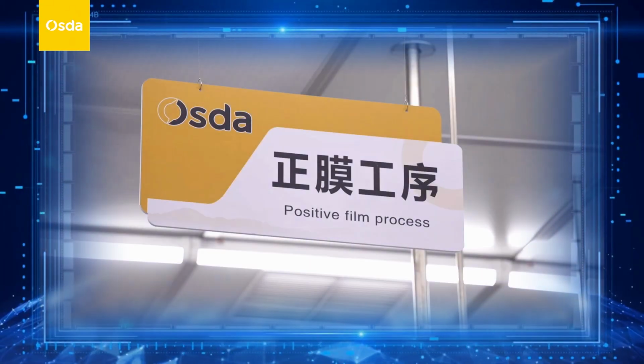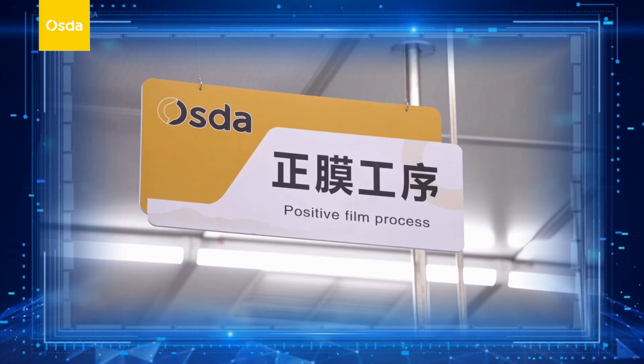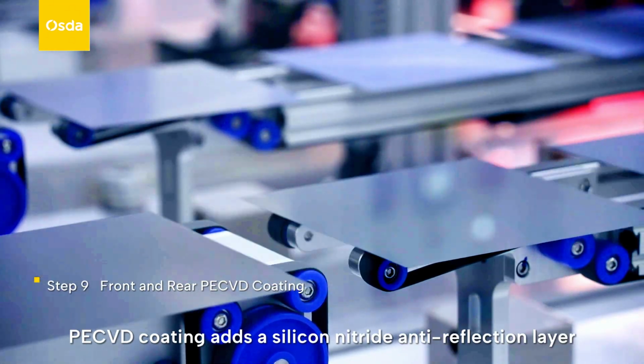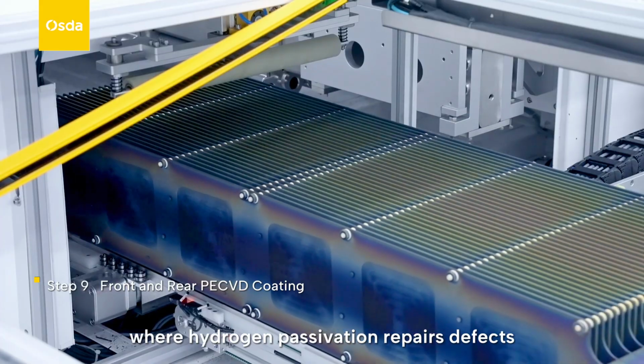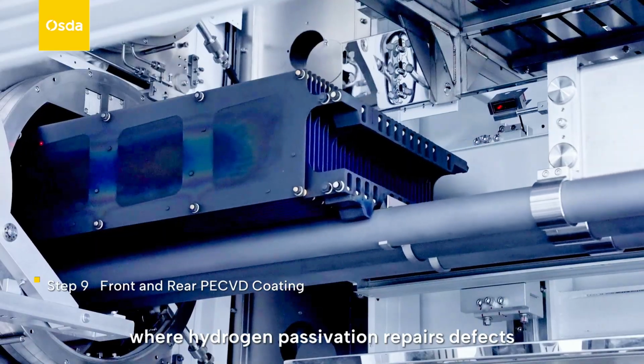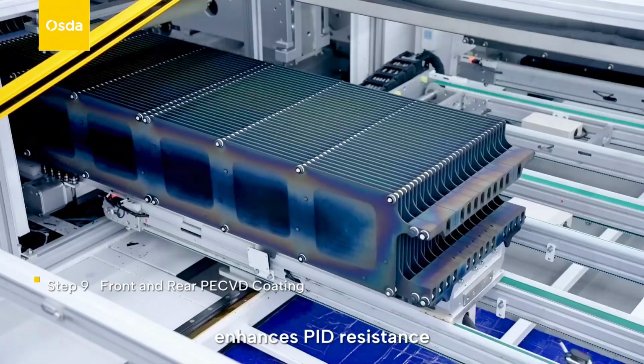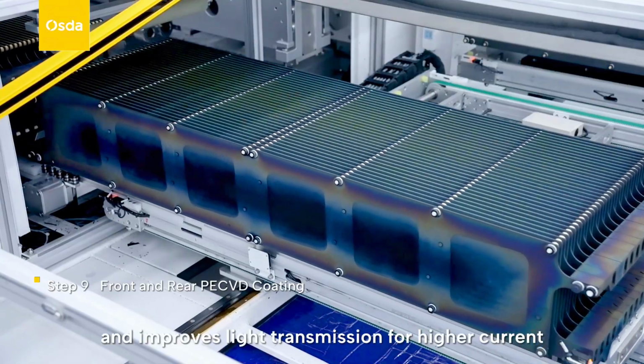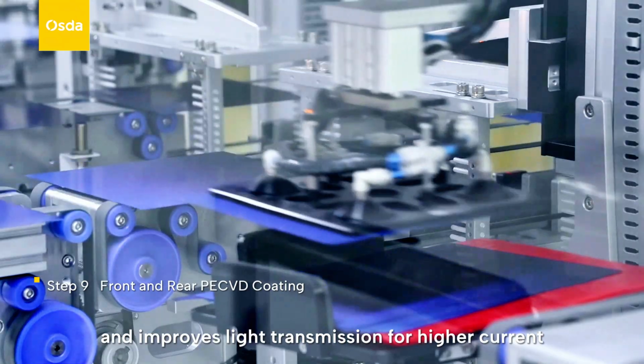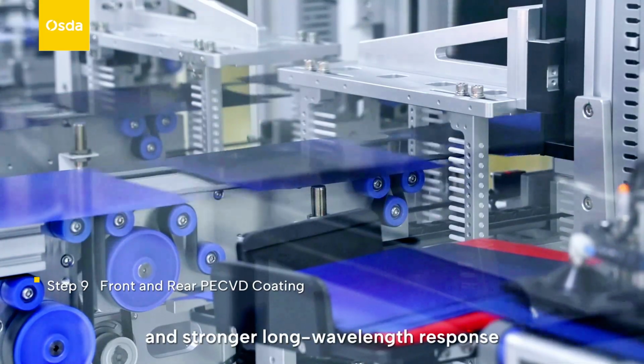Step 9. Front and rear PECVD coating. PECVD coating adds a silicon nitride anti-reflection layer, where hydrogen passivation repairs defects, preserves passivation quality, enhances PID resistance, and improves light transmission for higher current and stronger long wavelength response.